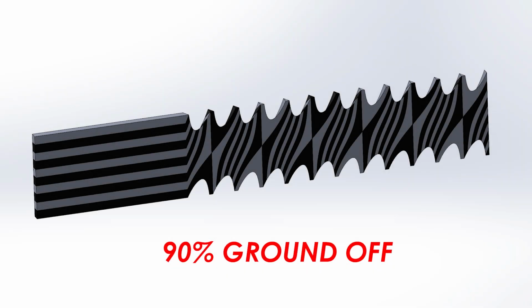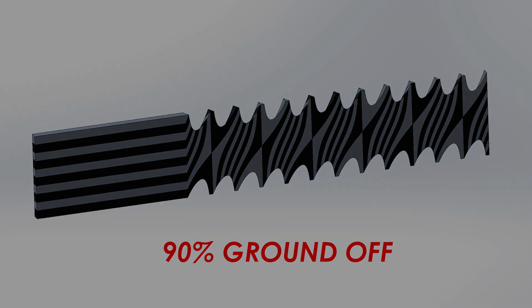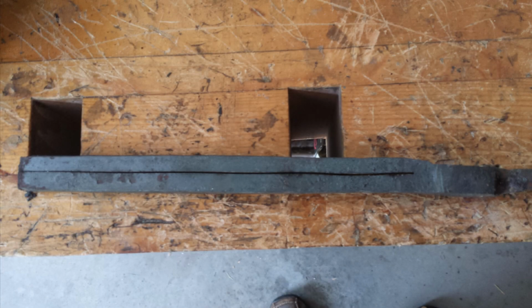At 90%, we get the same pattern as we did with 10%, with the difference that the slanting, again, is in the opposite direction. So one could conceive the idea that if instead of grinding the bar and waste all that metal, we were to saw the bar at its length, then we will end up with more material with different patterns to play with. This is a plausible explanation, as it is unlikely that the smiths in the 8th century were very keen on wasting precious metal that took a long time and a lot of effort to produce in the first place.